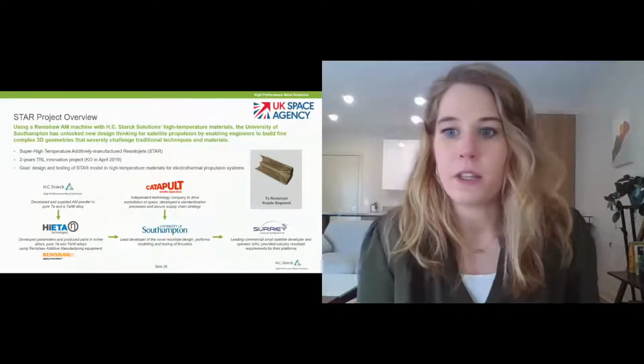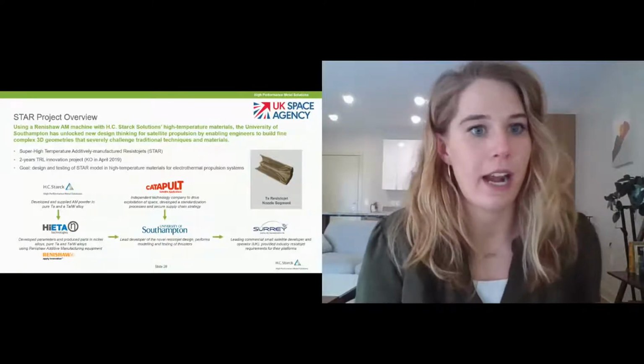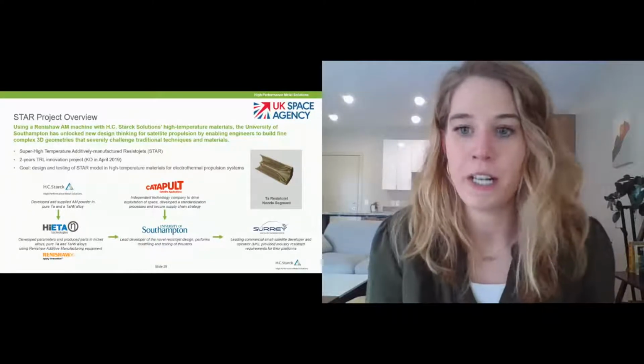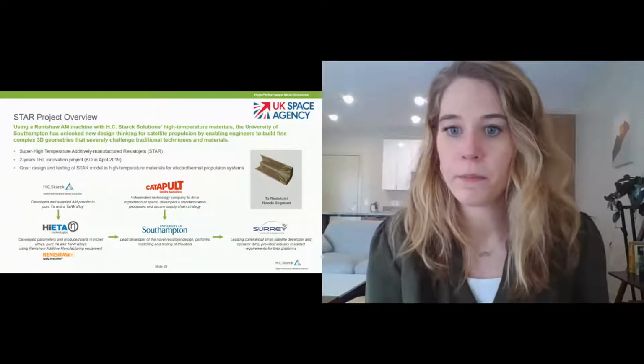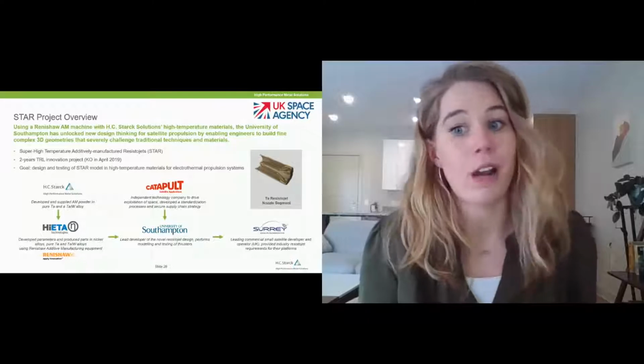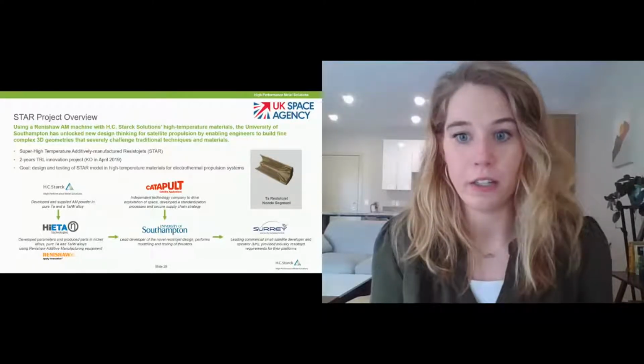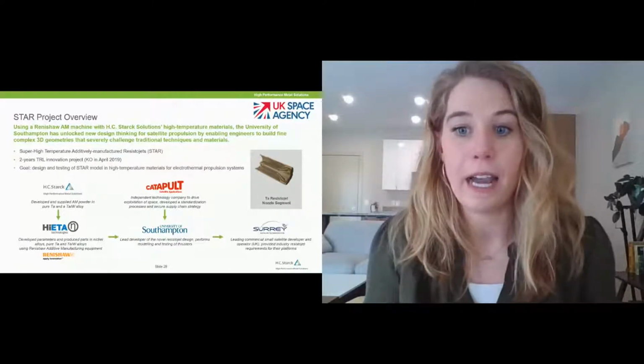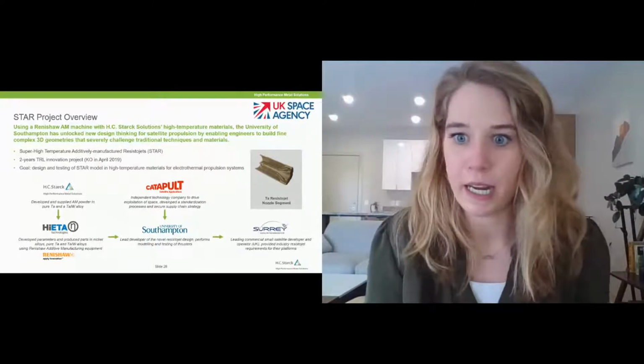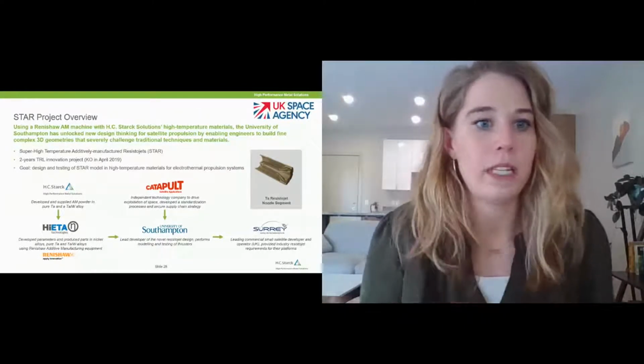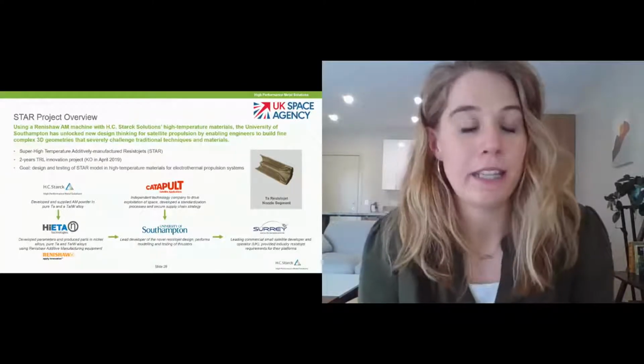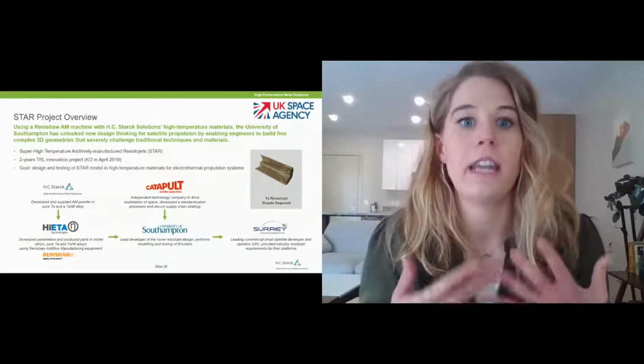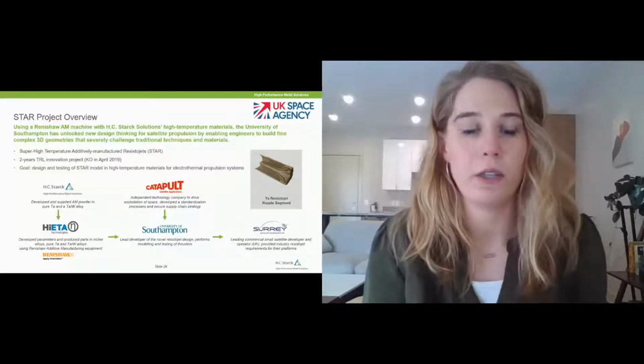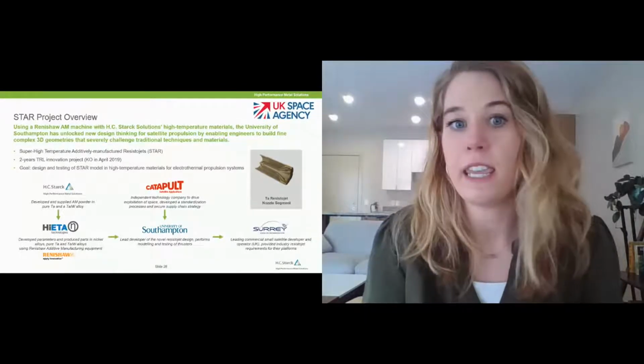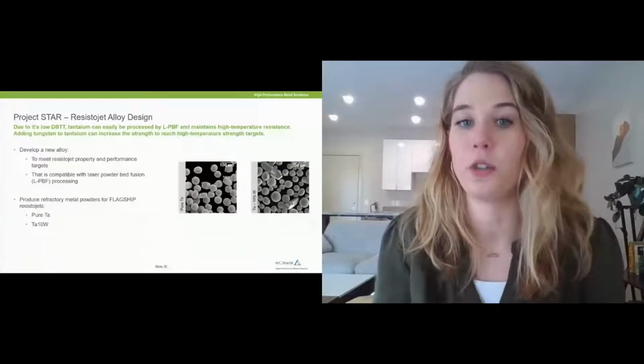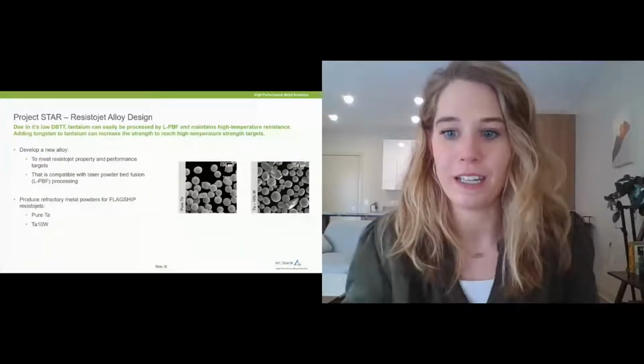So as I previously mentioned, tantalum is a refractory metal that has a low ductile to brittle transition temperature. It was below room temperature, and so therefore it can be easily processed using laser powder bed fusion technology while still maintaining its high temperature resistance in the as printed state. So we decided to provide tantalum and tantalum 10 tungsten. Adding tungsten to the system can also increase the strength even further to reach those high temperature strength targets that the resistojet needs.